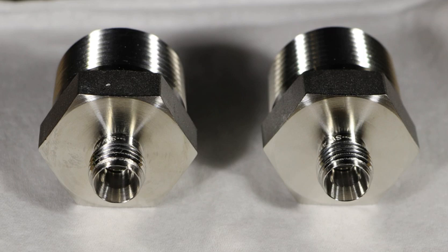Stainless steels are corrosion-resistant, but they are not completely impervious to rusting. One common mode of corrosion in corrosion-resistant steels is when small spots on the surface begin to rust because grain boundaries or embedded bits of foreign matter such as grinding swarf allow water molecules to oxidize some of the iron in those spots despite the alloying chromium. This is called rouging.